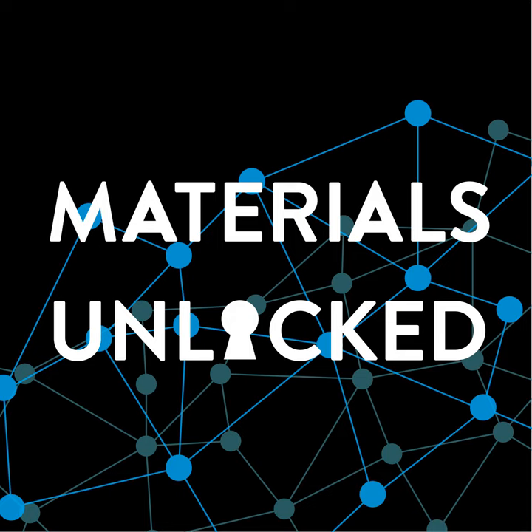That's creep, basically. But that has huge implications in a design space because it obviously modifies your geometry of the component. Eventually, it will start to lead to failure of that part, rupture, plastic collapse, because the material will become so deformed, so thinned in regions where it's deforming, that actually it can no longer tolerate the stresses in that region and will fail. So that's what we refer to as a creep rupture life of a component. And for some of the steels we're looking at, such as ferritic-martensitic steels, those creep lives are very low at high temperatures.